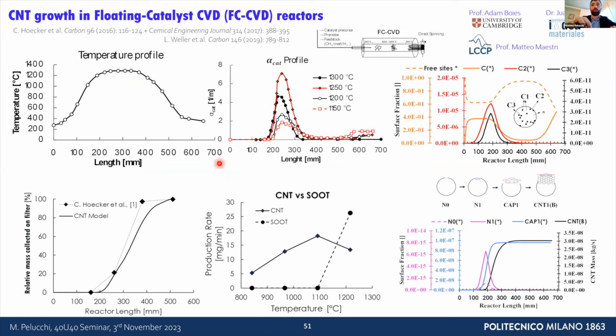We can start to make predictions. You can see here the evolution of the pseudospecies I described before. On the bottom left, you can see the comparison between our model and the experimental data by Adam Boies and co-workers, which is in relatively good agreement. Again, this is probably the only dataset we can simulate at the moment.